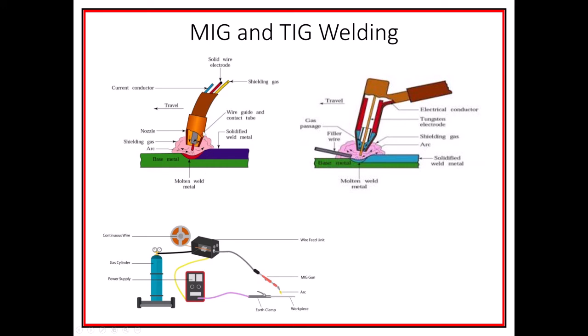So you can see right here, I believe over on the left is the MIG right there. But once again, the arc or the electrode is not the same as the filler material in the MIG and the TIG. One could be wire fed through a machine. Another could be sometimes you're holding the filler wire over to the side. And the speed of the travel, the speed at which you're moving the thing back and forth, the speed of the filler wire, and also the flow rate of the gas, this can also blow the puddle away, so you have to be careful with that. And you also have the amount of voltage or amperage that you're putting into this. All of those need to be manipulated, and some of it has to do with the thickness of the material. Because if you have a very thin material, having too high of a temperature will blow right through.